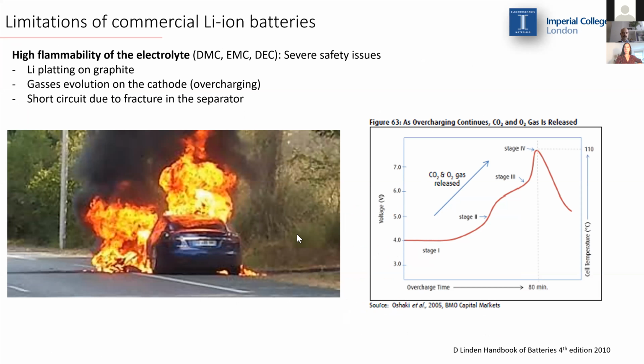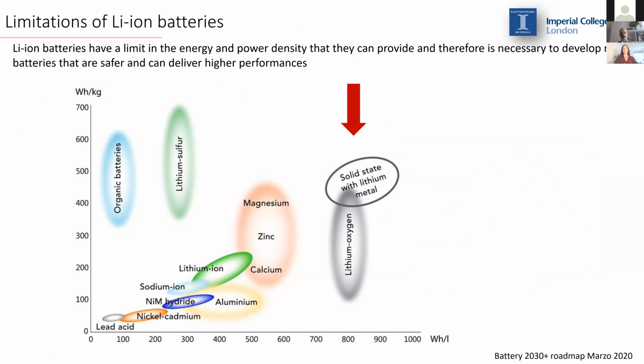That is a rapid increment of the temperature associated with different issues like lithium plating on the graphite, gas evolution due to overcharging in the cathode side, or short circuit of the cell due to fracture of the separator. I'm sure most of you have seen Tesla cars in flames, but also problems with mobile phones. So these two limitations, the electrochemical stability window and the safety, are limiting the applicability of the lithium-ion technology that we have at the moment.